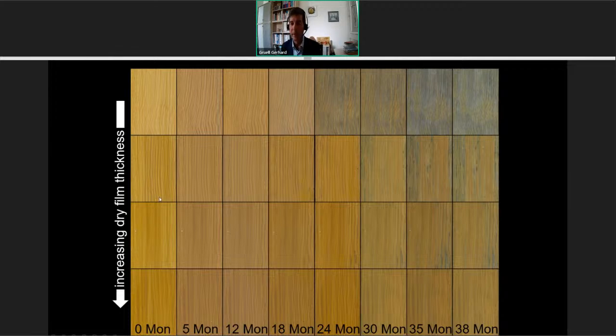And we used the definition of maintenance intervals on this set of samples, and we figured out that here in the red rectangles, we found the stage where maintenance coatings would have been needed to retain the integrity of the coating film. And if you look at these stages, you see this is relatively early, where some experts would say, no, we still don't need maintenance, it's still in very good conditions. But if you look in detail, for instance, here on this sample, you see a small crack here, which is a defect that needs maintenance to retain the coating film. Some users and some people would say, I need maintenance here, but by our definition, which has been discussed with experts as well, this is too late for a maintenance coat. This would need a removal of the old coating film and a new coating built up from the primer.